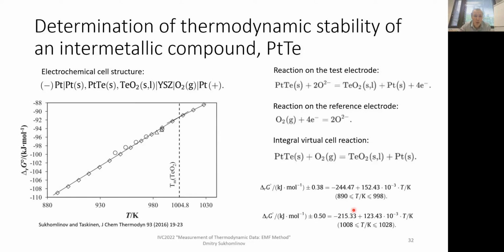We build a galvanic cell with such a structure. Our test electrode contains platinum, platinum telluride, and tellurium oxide. Let me say about the reaction on the test electrode first. Platinum telluride plus 2 moles of oxygen ions equals tellurium dioxide plus solid platinum plus 4 electrons.